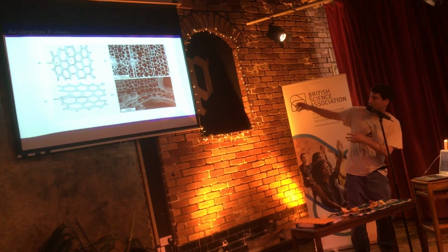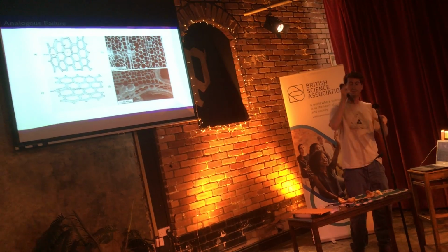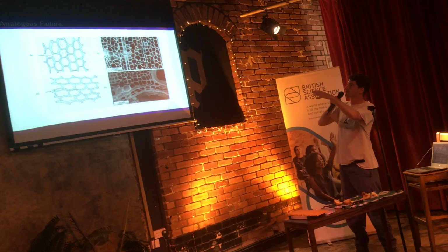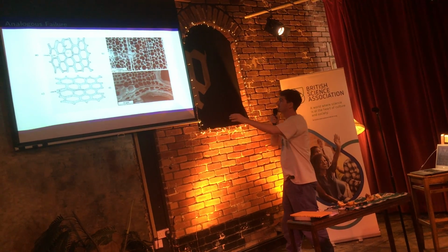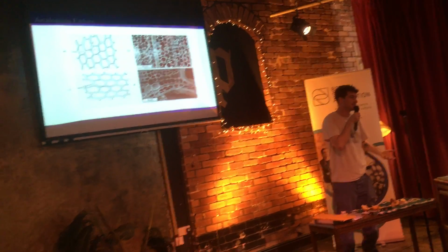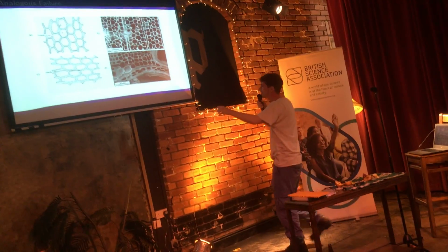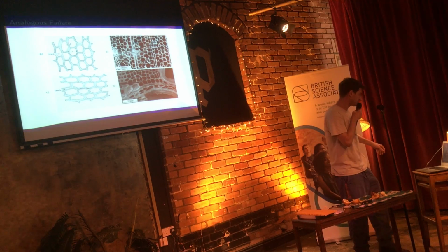So just to highlight, this is wood, and either we can crack through the center of the cells, and that's them bursting, or we can crack between the cells, and that's the same as debonding. And generally that's only going to happen if the cell walls are thick enough that they can support that crack that goes through it.